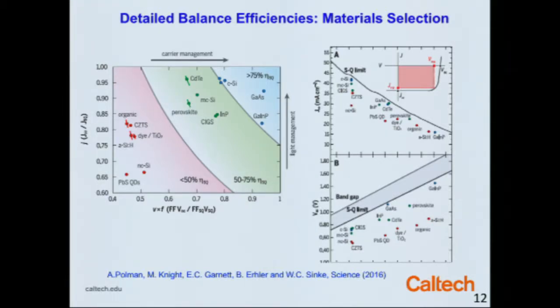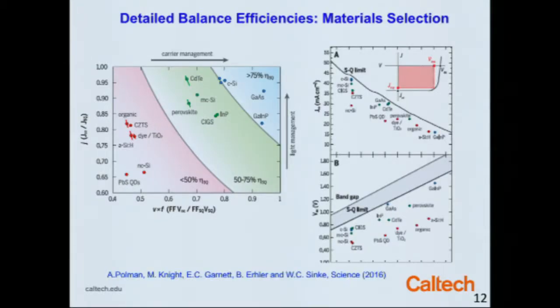So obviously we would like to be up here. And you can see there are several materials that are quite privileged in this regard. One is crystalline silicon. We have this incredible number of cycles of learning that have come through manufacturing, and you can see that has resulted in silicon getting almost an optimal photocurrent density. But it's still a little ways away from the voltage limits, so there's still work to be done.